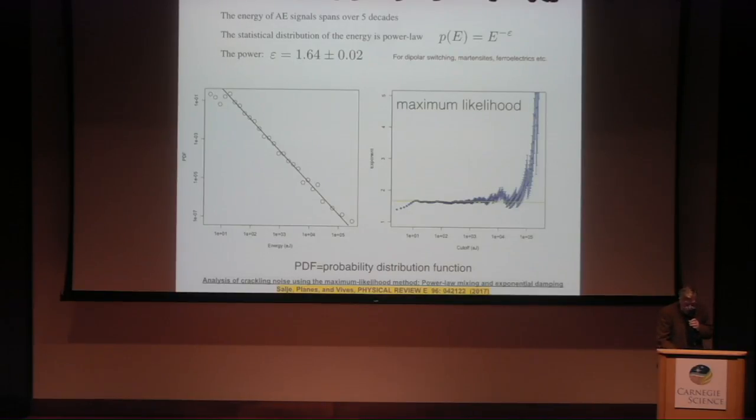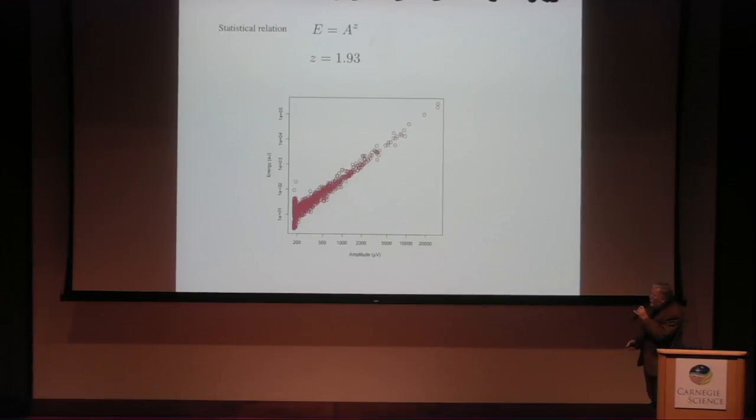In particular, the Barcelona people are very good. You look at the energy which is transmitted as a function of the amplitude you put in. And you know energy is always amplitude square, roughly speaking. Now, in these fast processes, that's not exactly true. It's amplitude square minus epsilon, because the profiles are different. So you determine these exponents, and they're typically in the order of 1.9. So it's a little bit below the square dependence.